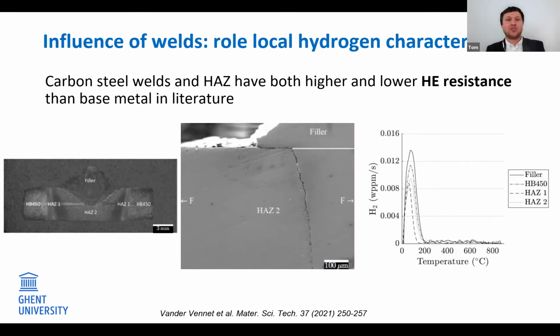But as you can see on the right-hand side, we do thermal desorption spectroscopy. With this method, we can measure the concentration of hydrogen. The filler material can take up the most hydrogen, as you can see in this graph on the right. And this was the reason that the crack initiated in the filler material. Much more research is, of course, needed in this field.